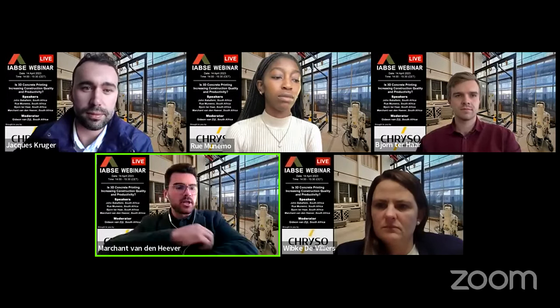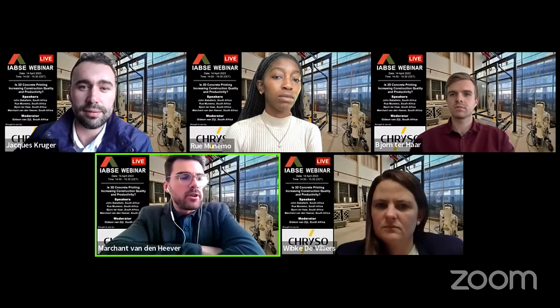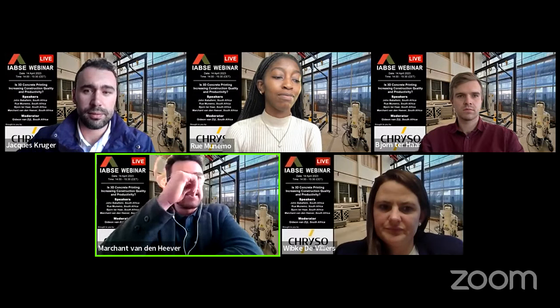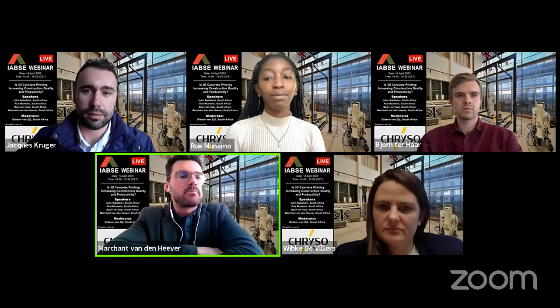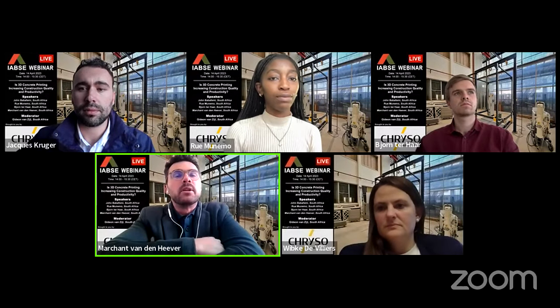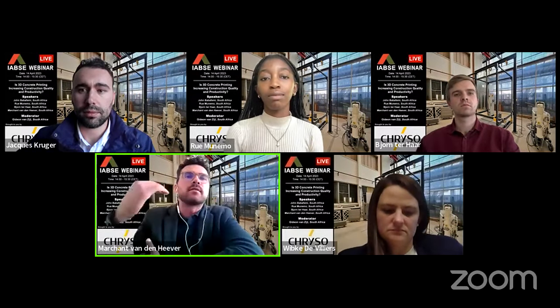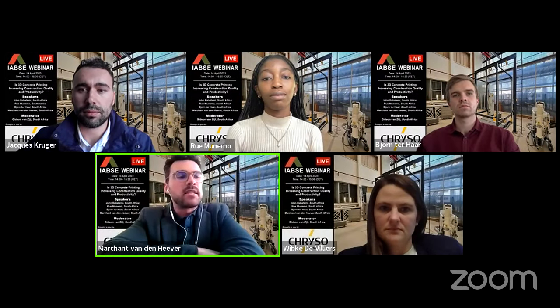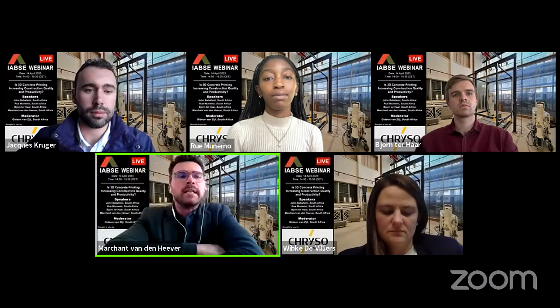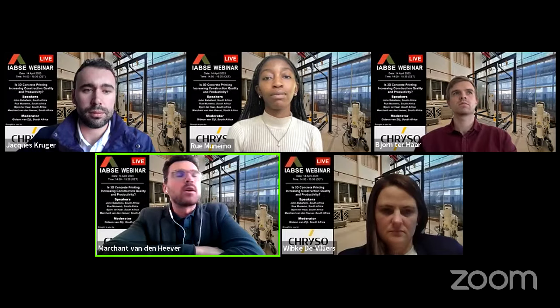Yeah, thanks very much, Jacques. So I think the question is twofold. The first one, in terms of a technical limitation, no, there's no technical limitation to the overall height of a building that you can print. However, there is a limitation to the height that you can print within a certain amount of time, and that is a material constraint. Your material has a physical building performance, so you can gain a certain height during a certain period. And that's linked to your structuration rate. Now, obviously, you can have an infinite amount of sequential procedures where you print sections, and then another section and another section. So that would more be an equipment constraint.